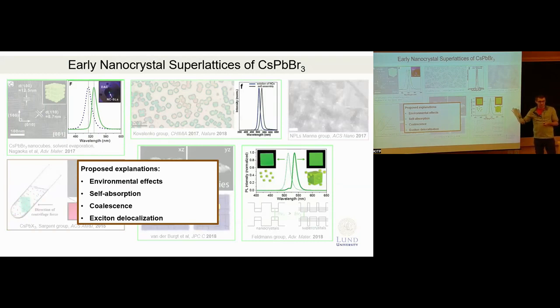and that somehow contributes to the redshift. And then another explanation, for example, in that early work, was exciton delocalization. So it was proposed that in these superlattices, nanoparticles are so close that there is an overlap of the excitonic wave functions, and there is a formation of mini bands, and that's what causes a redshift.